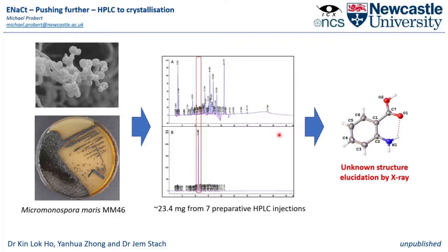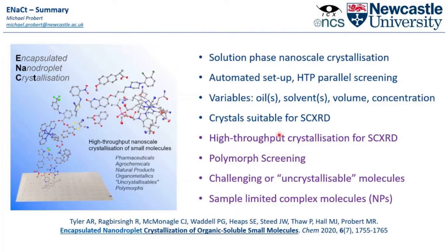If we then look at a summary, we could go through these things and say that this encapsulated nanodroplet technology seems to work very, very well. Its solution phase gives access to things which classically have not been accessible through solution phase in some cases. It's a semi-automated setup. We've got much higher throughput, so we can do parallel screening. The amount of material we require is really quite small. We have a wide range of variables that we can approach to alter the success rates of our crystallization, and